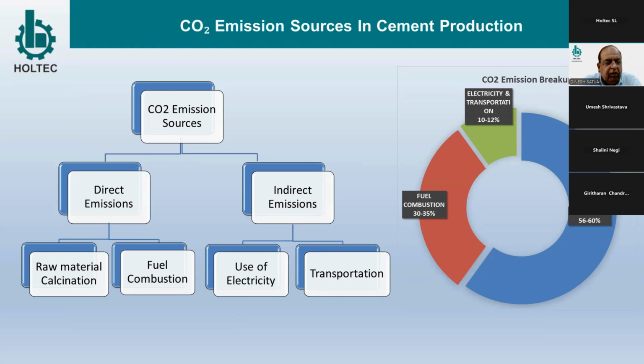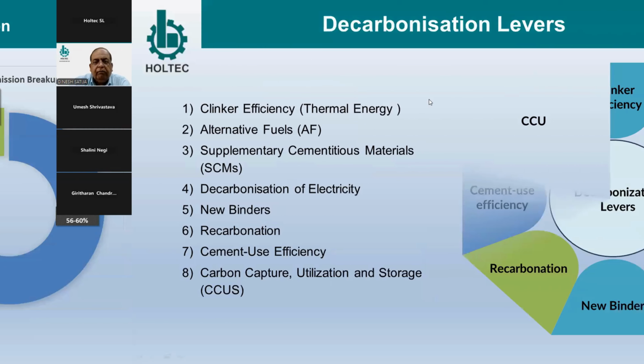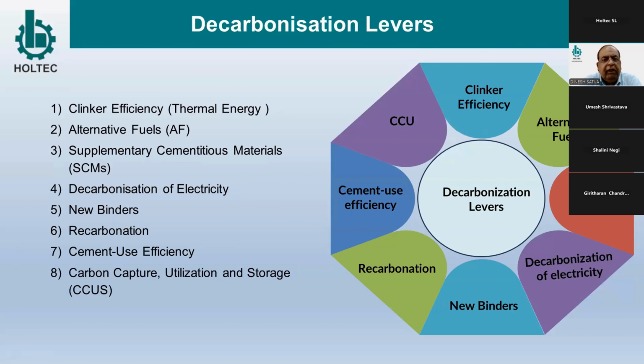Direct sources include raw material calcination. We know, being in the cement industry, that limestone, once calcined, emits CO2. So that is one of the major sources, which contributes about 56 to 60%. Another source is fuel, because India has a coal-based cement industry. So coal-fired fossil fuel is a major source, where around 30 to 35% of CO2 comes from. The rest, indirect, is the use of electricity and transportation, which contributes about 10 to 12% in the overall scenario.